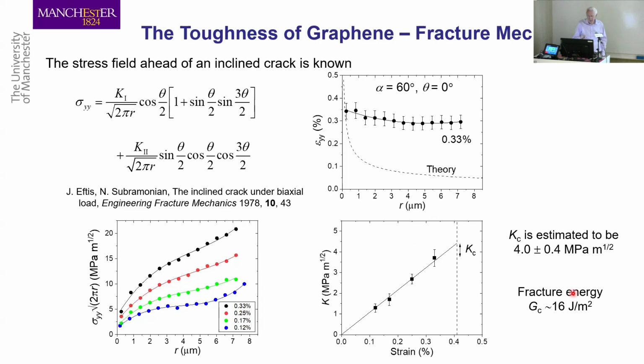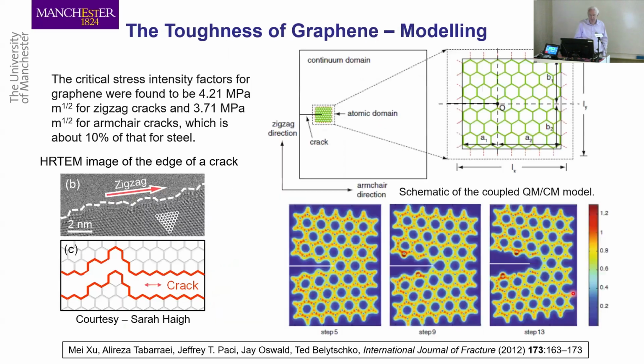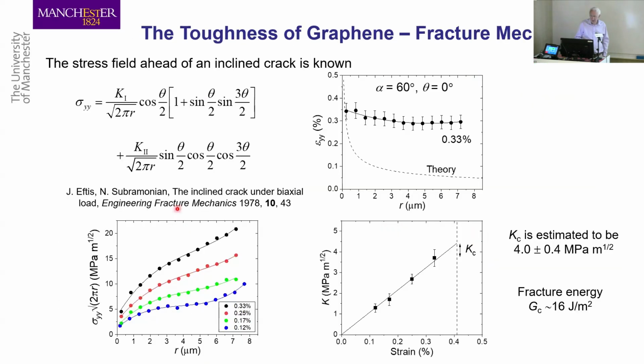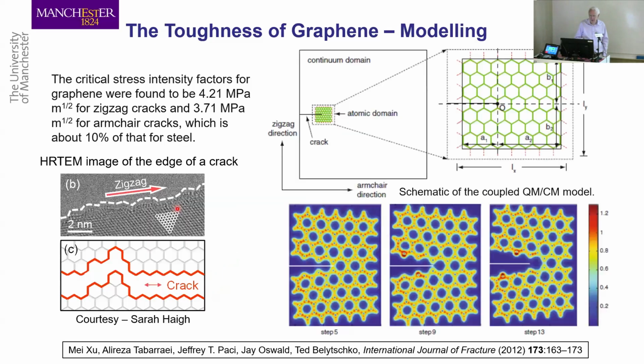But anyway, we can do this. And of course, in the literature, people have calculated this. They've calculated it in this particular paper here, International Journal of Fracture in 2012. They calculated Kc for graphene to be between 3.7 and 4.2. And we measured 4.0. So we're pretty happy that we measured the actual value.